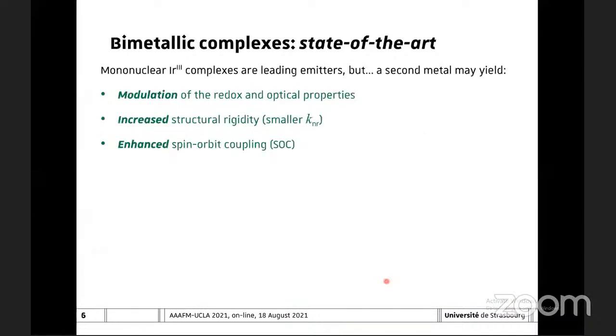So if you now look at the literature, main efforts have been devoted to the development of mononuclear iridium complexes. They are currently leading emitters, but the presence of a second metal may bring some interesting properties. In particular, it will help us to better modulate the redox and the optical properties, to increase the structural rigidity, which means that we can somehow counterbalance the energy gap law by decreasing the non-radiative rate constant, and we could enhance the spin orbit coupling.